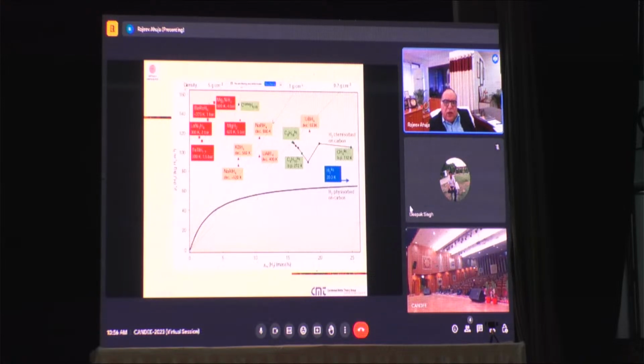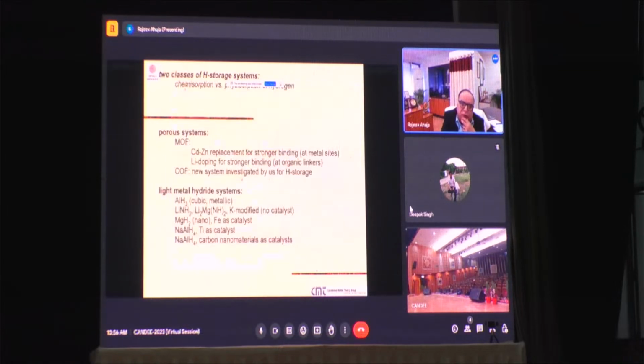And we can take any of these alanates, like sodium alanate. Here also we have 6 to 7% of hydrogen in the system. But the absorption temperature is more than 500 Kelvin. So either I can design a new material where this absorption temperature is low, or I can take this existing material and try some kind of catalyst to reduce the absorption temperature. That will be a good way to design a new material for storing energy.